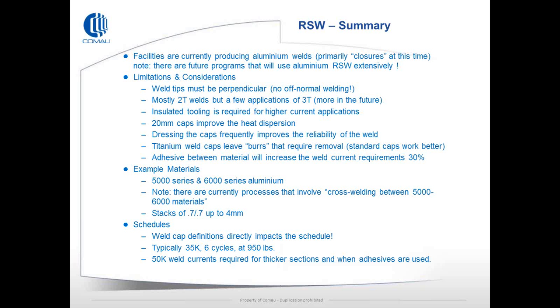Adhesive between the material will increase the weld current requirements significantly. Example materials, 5000 and 6000 series materials are currently being successfully welded, and stacks up to multiples of 4mm. So in terms of the actual stack configuration, it's quite significant. In terms of schedules, weld cap definition particularly impacts the schedule, so any contamination can dramatically affect the quality of the weld. Typically about 35K in terms of current, and about six cycles, and 50K on the greater materials, depending upon the actual process.